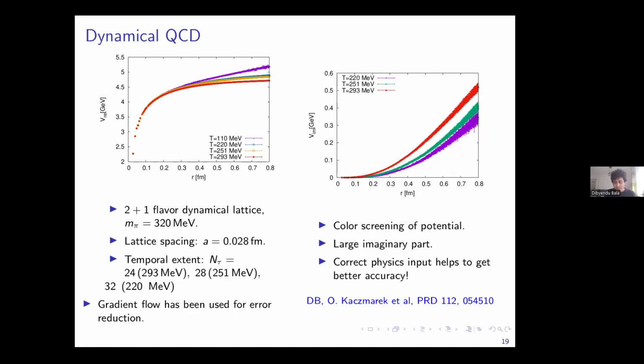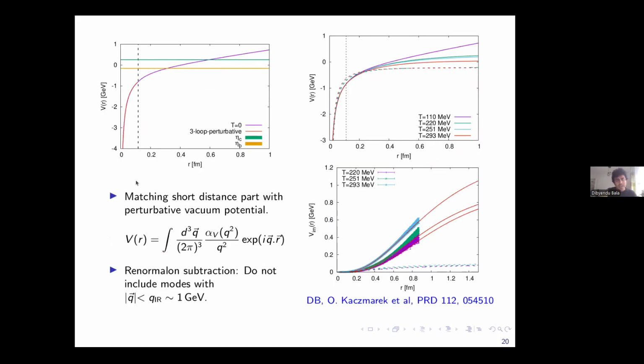Okay, so at short distance, there will be some zero temperature lattice artifact because we are on a finite lattice, and sometimes it shows up that the hypercubic symmetry of the lattice shows up, which is relevant at short distance, and therefore we have to replace this short distance part. And the way we did it is we replace this short distance.